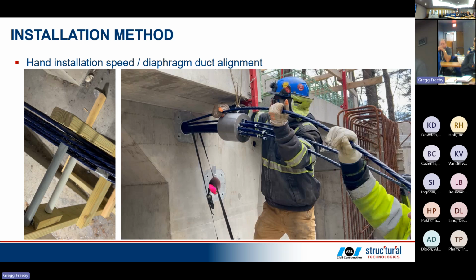ducts at these points. The challenges in ducts could be from a little kink in the shape from the precaster. Of course, that caused significant challenges on 2 particular tendons. Or it could be just a deformation in shape. Could be maybe just a little bit of epoxy inside. Because I think on site we'll have a cut sample of a 6-12 duct, and you'll see 12 strands in there. There's virtually no other space to accommodate any deformations. It was super tight.